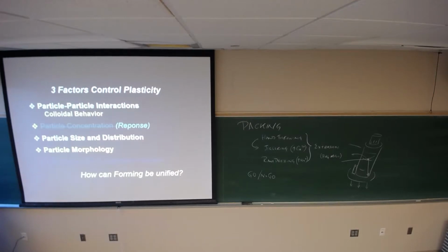So I have 3 now variables that control plasticity. Now you can argue that this rheology, the suspension being done here, is valid for non-intrinsically plastic systems, meaning that if I go to alumina, zirconia, or silicon carbide, this plays a role because I'm going to put polymers in the system, and that's changing that rheology of the medium. Okay, I'm not entirely sure that that's a valid approach, but these 3: particle interactions, my degree of dispersion, or my ionic strength. I increase ionic strength, right? I'm going against dispersion. But what happens is, in a suspension, my viscosity goes up. In a plastic body, the system gets softer. So sort of an inverse of behaviors, we'll look at it that way.